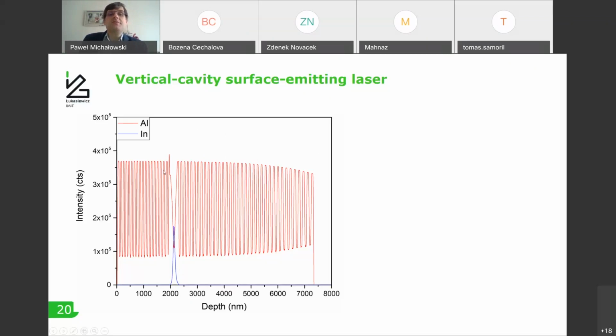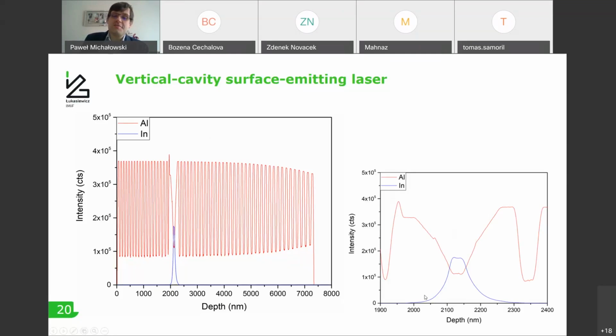So basically when you use standard SIMS, this is already quite a nice result, but you can see that first of all, the thickness of these layers should be identical, whereas it seems that they are getting thicker and thicker as the depth profiling progresses. And also, we do not really see any well-defined quantum wells here.